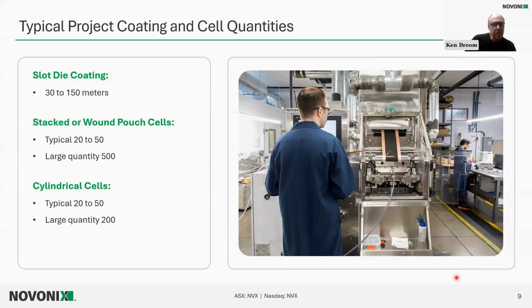And for stacked and wound pouch cells, typical quantities are 20 to 50, especially if we're doing material evaluations. That's a typical quantity, but sometimes customers want a lot of finished cells or dry cells from us, and we do quantities up to 500. Similarly, for cylindrical cells, typical is 20 to 50, and large quantities are around 200.